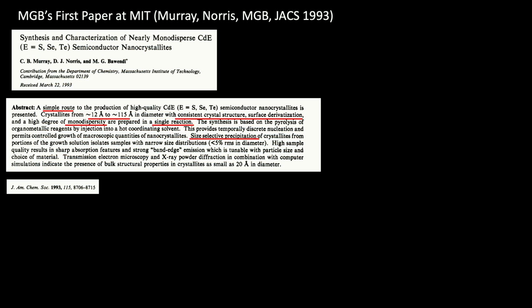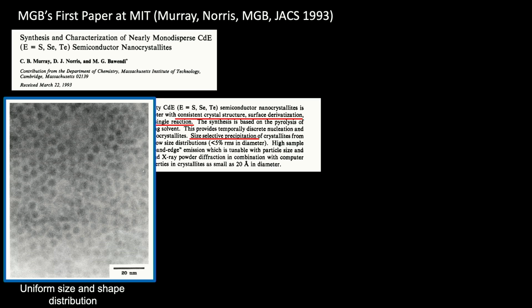We were still chemists, so we knew we had to purify things. So when you make a new molecule, you have to purify it, right? You do whatever you need to do. So Chris Murray invented a precipitation, which we call size-selective precipitation. By slowly titrating a non-solvent, we could get the biggest particles out first, get rid of the biggest particles, keep whatever is there, do it again, and get rid of the solvent. And now our precipitate is a really narrow size distribution, purified. All the precursors are gone. It's a pure precipitate of quantum dots.